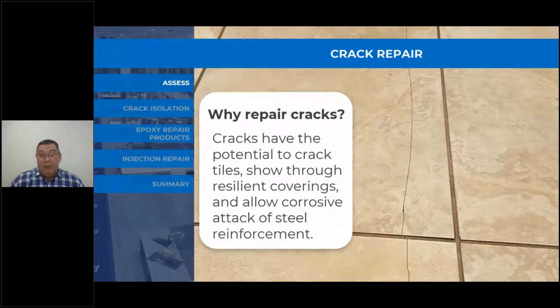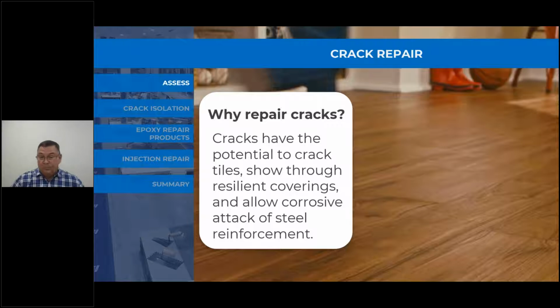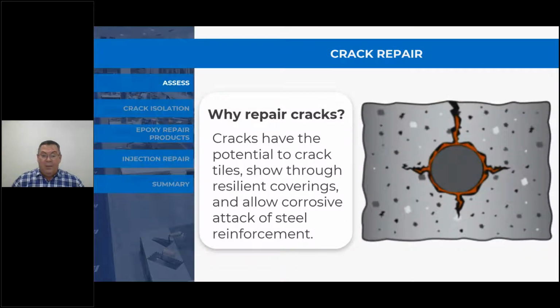So why do we repair cracks? Cracks have the potential to crack through tiles, show through resilient floor coverings like vinyl and lino, and they also allow corrosive influences to attack the steel reinforcement. Water and contaminants can get down through cracks and reduce the passivating layer, or the alkalinity, of the concrete surrounding the steel, and subsequently cause steel reinforcement corrosion and ultimately a degradation of the concrete element.